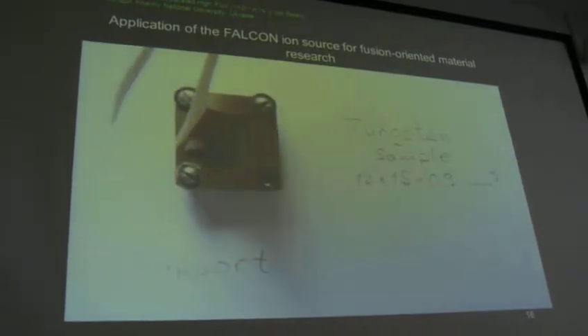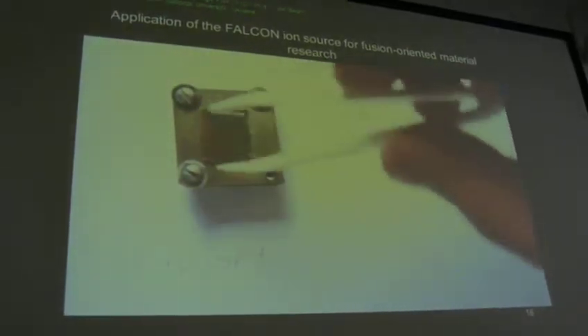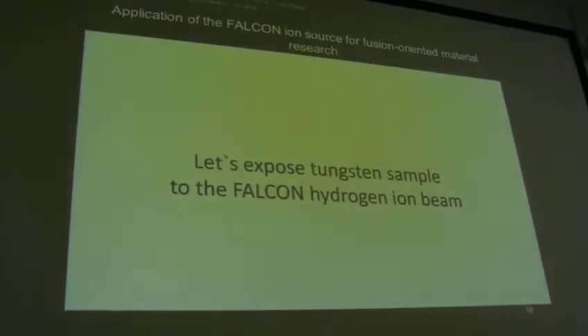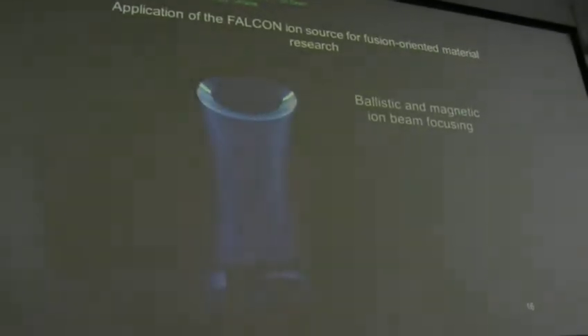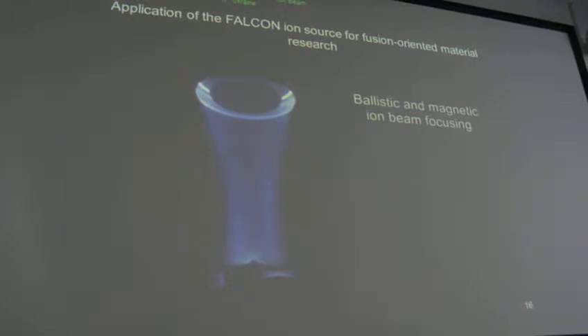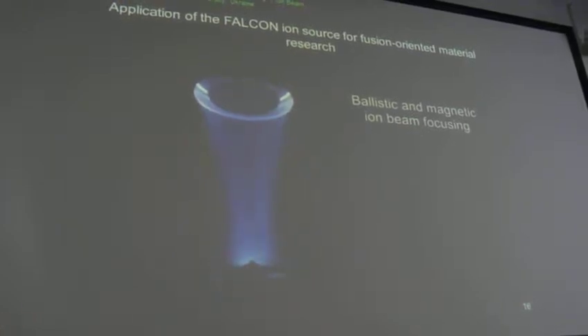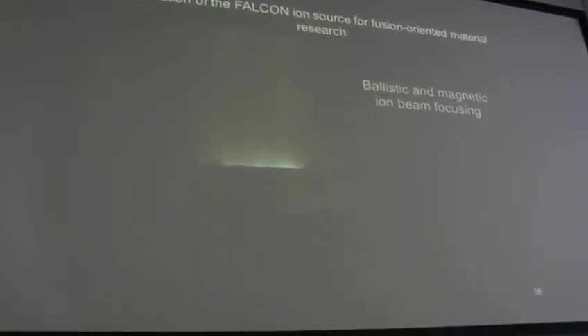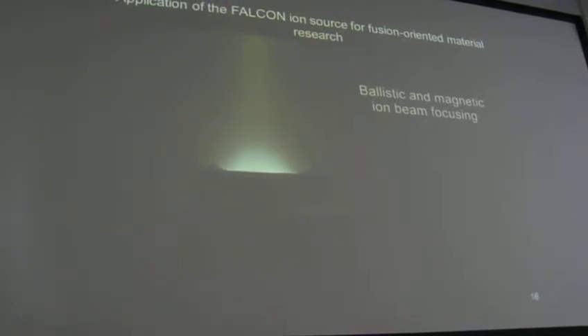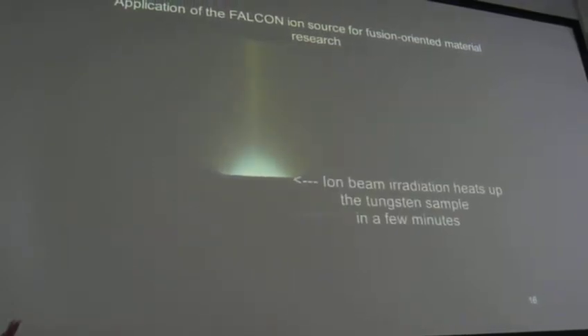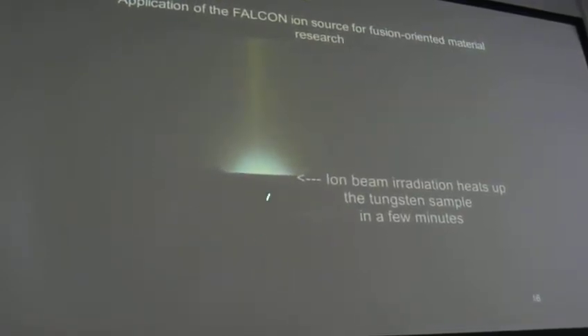We can see how the tungsten sample is placed on the holder. It's a movie about the application of the Falcon source for fusion-oriented material research. Then the tungsten sample was exposed to the hydrogen ion beam. And now we can see the ballistic and magnetic ion beam focusing in action. Ion beam irradiation heats up the sample in a few minutes.